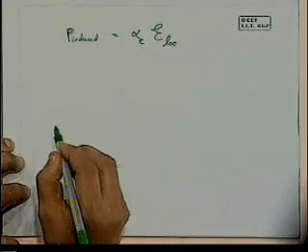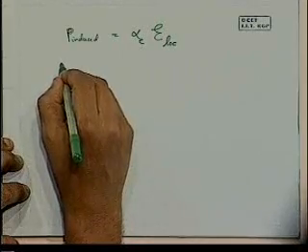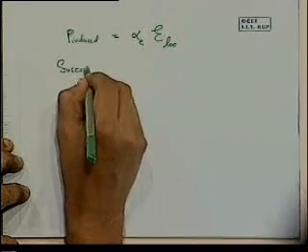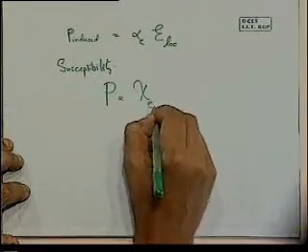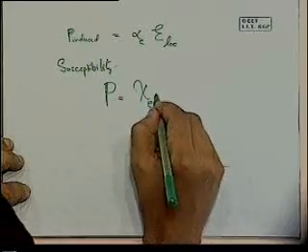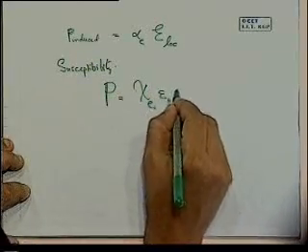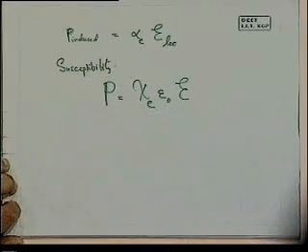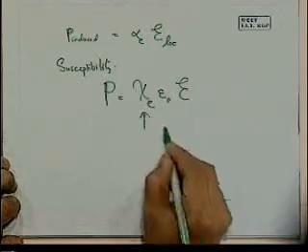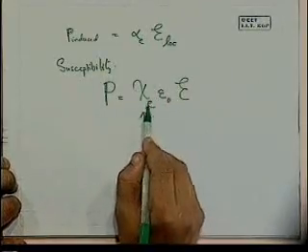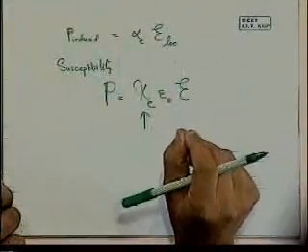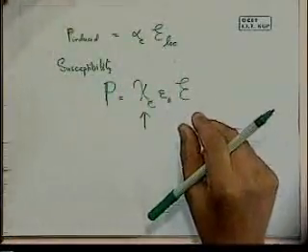And we earlier defined electric susceptibility in terms of the following: the polarization, capital P, is equal to chi, which is susceptibility, times epsilon naught times the applied field. So the definition of susceptibility comes out of this equation, and it is not affected by our consideration of a local field. We can still use the external, the average value that is applied. So I've got this equation unaffected by the fact that each individual dipole is now affected by a local field and not simply by the average field.